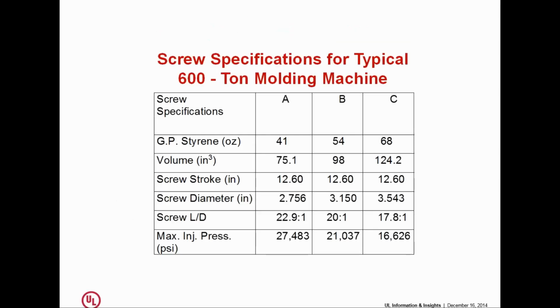So let's take a look at just one example of this. This is just a 600-ton molding machine. Doesn't matter whose it is. It's basically the same deal throughout. We tend to talk about our machines in terms of two conditions, the tonnage and the shot size. Shot size being the maximum amount of material we can actually deliver if we stroke the entire travel of the screw from all the way back to all the way forward. And we basically couch this in terms of the weight of material that we can extrude in terms of general purpose polystyrene. So in this particular case, we have the option of a 41-ounce barrel, a 54-ounce barrel, or a 68-ounce barrel that we can buy with this 600-ton molding machine.